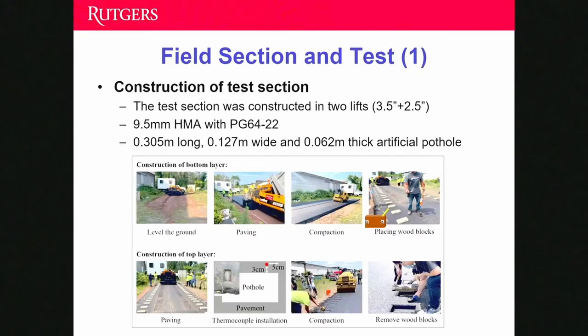And in the field, we had a test section at Rutgers campus. We built it like 2 years ago, also for this project. The test section was constructed in 2 layers, 3.5 inch plus 2.5 inch. And the construction material was the same as the HMA in our patching material. And we made some artificial potholes during the construction.